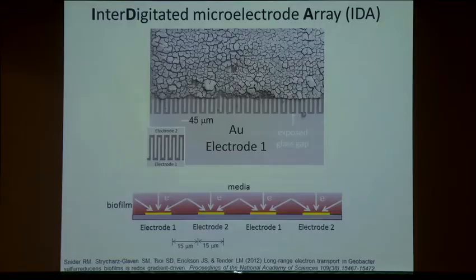So here what we've done is poise both electrodes, all the electrodes, at an oxidizing potential. We usually do 0.3 volts versus silver chloride. And in the presence of Geobacter and under electron acceptor limiting conditions, we can grow a biofilm on these gaps. And if the architecture of the array is such that the separation between the bands is on the order of the thickness of biofilms, we usually get 20 micron biofilms in thickness, and we have 15 microns here in gaps, we can actually get the biofilms to grow and then fuse together and form a confluent biofilm on the electrode surface.